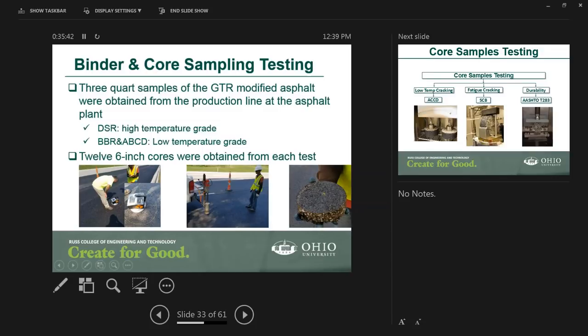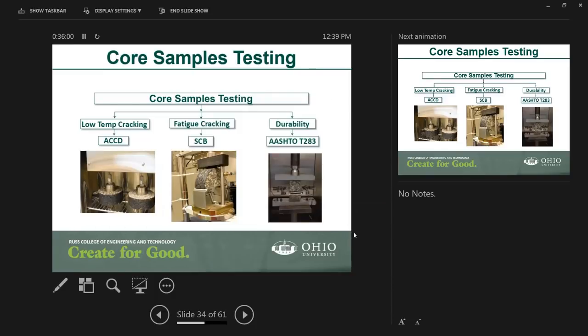For those of you who are not familiar with the ABCD, it is the asphalt binder cracking device. Again, it was developed by my colleague as part of a national study. It's an AASHTO approved test. On the cores, again those 6-inch cores, we evaluated the low temperature cracking. We also evaluated fatigue cracking. There was a new test procedure adopted by some DOTs, including Illinois, which is the semi-circular beam test, the SCB. Therefore, we used that to evaluate the fatigue cracking. And then we also evaluated the durability using the AASHTO T 283.